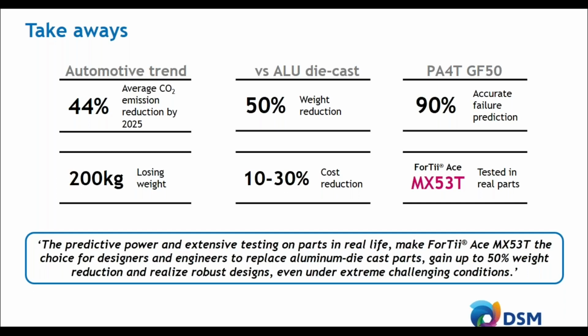Going from steel to aluminum already helps with reducing that weight significantly. But also a next step can be taken from going from aluminum to an engineering plastic. Around 50% of weight reduction can be achieved. And there is also the potential to reduce the cost by around 10 to 30%, depending on the secondary operations that are normally needed for the aluminum die-cast operation.